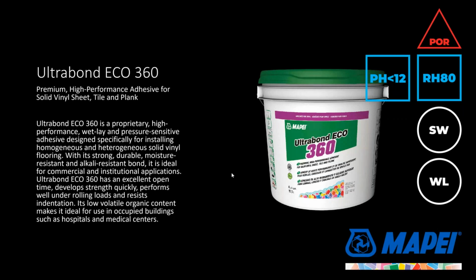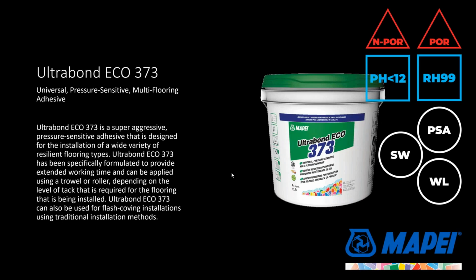Moving into something that's a little bit newer to the marketplace, Eco 373 took the LVT market by storm a couple years ago. This was a highly aggressive, pressure sensitive adhesive designed for use on slabs that are 99% RH. Porous and non-porous substrates, pH is less than 12. It got its claim to fame by using the pressure sensitive adhesive mode. What contractors would do, they would spread 1,000 square feet, let it all flash off, and then just come in and start throwing luxury vinyl plank on the floor like dealing cards out of the deck in Vegas. It was very fast, very easy to go.